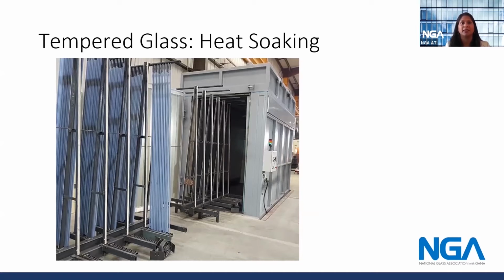So heat soak testing is done on fully tempered architectural glass. It can be done on clear glass, tinted, low iron, patterned, or any type of coated glass. Within North America, there isn't a test standard. However, there's a European standard, EN 14179, that talks about two different types of heat soak. There's an inline heat soak testing, and then there's also a batch testing. Where it comes to the industry, heat soak is not a guarantee that you're not going to have spontaneous breakage.